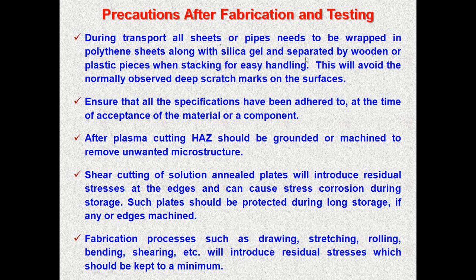During transport, all sheets and pipes need to be wrapped in polythene sheets along with silica gel. And when stacking for easy handling, plastic pipes should be separated by wooden spacers or so. This should avoid normally observed deep scratch marks. Ensure that all specifications are adhered to at the time of acceptance of the material.